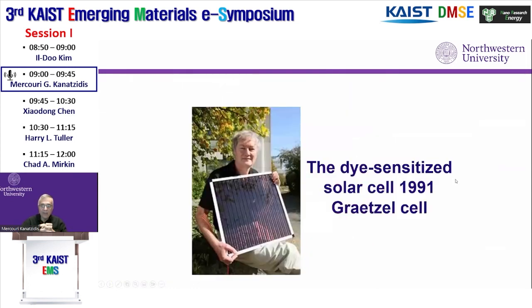And now, I believe we have to give credit to Michael Gratzel for this field being what it is, because before the perovskites, there was another solar cell that we call the Gratzel cell, or dye-sensitized cell, that was announced in 1991. And that cell was also similar in the sense that many chemists could actually be involved, because making the dye-sensitized cell was relatively easy, because it involved only chemical solution processing. And so Michael Gratzel made this cell, and it reached about 10% efficiency by around 2011, which was remarkable.